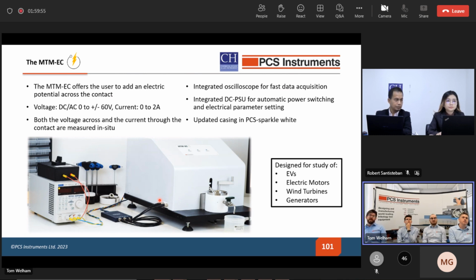In addition, we have an oscilloscope which is connected to the MTM, and this is also integrated into the PCS software. So we are able to capture very high sample rates and see discharge events as they are occurring in real time. We have automatic power switching on for automatic testing, so it's very easy to set up and use for customers. And it comes with updated casings and electrical resistance switch boxes to allow a very wide variety of current, voltages and powers to be tested across the contact.